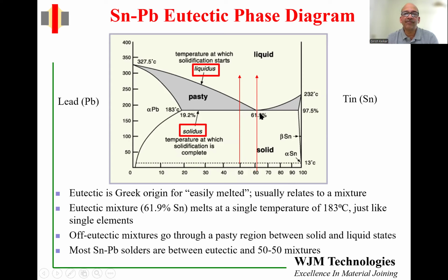The unique combination of mixture where we have 61.9% tin and the remaining is lead has the lowest melting temperature in this system. So the mixture of 61.9% tin and the remaining lead melts at 183 degrees centigrade, just like a single element. So if you take a special solder, and you can buy these, you can buy a eutectic solder, and you raise the temperature from room temperature, it's solid up to 183 and then immediately becomes liquid. So even if you're slightly more than 183, it's going to be quite liquid and fluid. This mixture, which is unique in that it has a lower melting point than both tin and lead, is called the eutectic. Eutectic is a Greek word for easily melted. That's where the word comes from: a mixture which is easier to melt than the base metals.